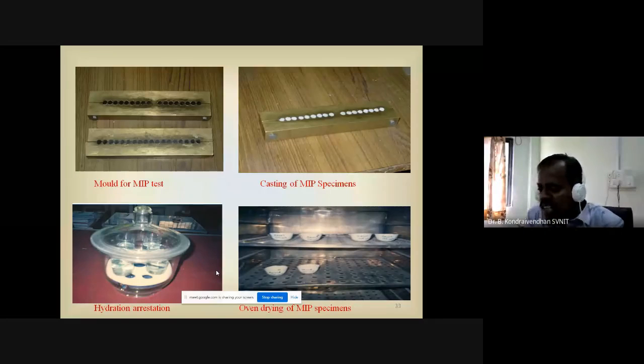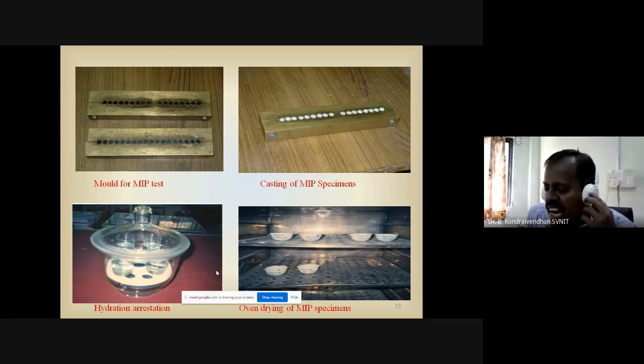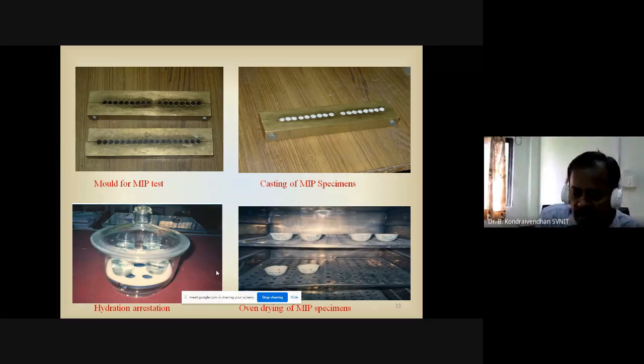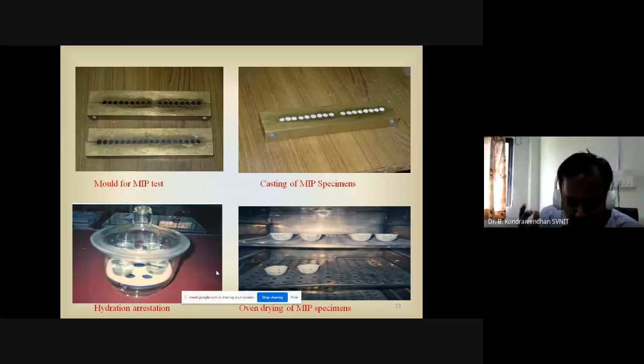Here we are using the oven drying technique. Accordingly, we have to choose the theta and gamma values, that is, the surface tension and the contact angle value. So that's why we have to use 117 as the contact angle and 0.484 as the surface tension. That's what I told you. There are 3 different drying techniques available. Here we have used oven drying. Some people use vacuum drying, some people use pressure drying. Here we adopted the oven drying method.